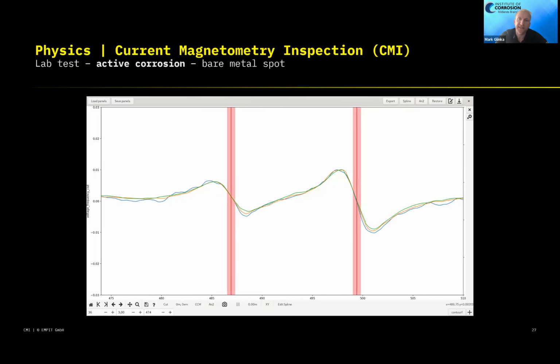Let's now go to the second case, and you can see what is changing. The frequency spread is more or less gone. Think about AC corrosion, for example. AC corrosion is a chemically active process, and it will make your pipeline corrode very fast. When you dig it up, you have this shiny metal over there, and obviously it's not possible that any protective layer will form over there because it's going to get destroyed by the AC interference we are having. And so you can see we then measure no frequency spread.